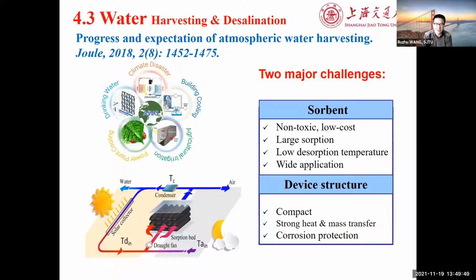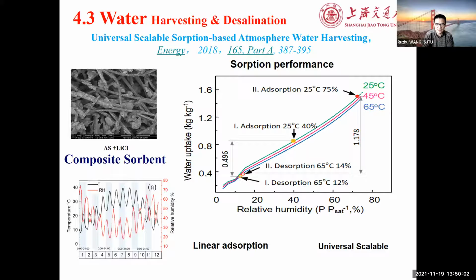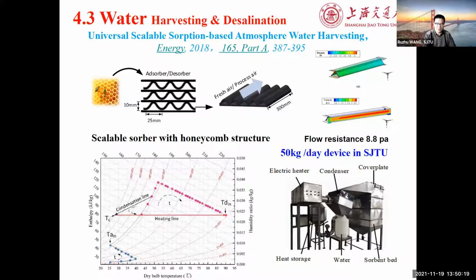And other work is on AWH. I published one paper in Joule on the progress and expectations of atmospheric water harvesting. We also developed simulations and data maps, because we considered that this kind of composite material could be very good and applied all over the world, whether in dry or humid regions. This shows the real operation: we developed 50 liters of water per day by solar energy, at a humidity of about 70%. When we tested at a relative humidity of about 35% in winter time, it's about 18 liters. So we considered it could be a universal, scalable sorption-based atmospheric water harvesting device.